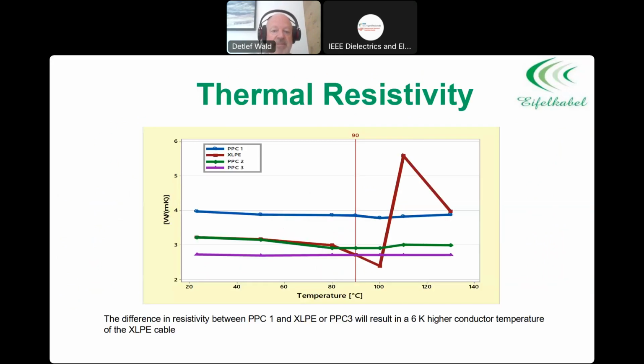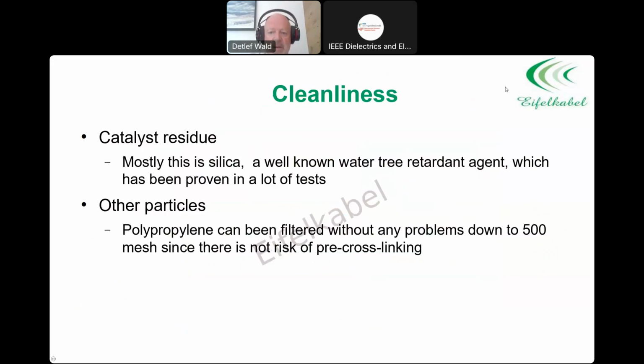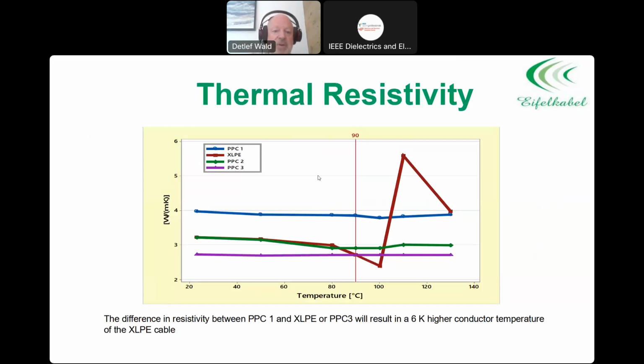Thermal conductivity, the other subject, like I already said, has also something to do with the density. So here's a comparison of XLPE with 3 different polypropylene compounds. The red one with the deep drop, or change, around 90-100 degrees, is the XLPE, and the green and all the other ones are polypropylene compounds. The blue one is a commercial one that is in service. The green and the magenta one are polypropylene compounds under development, where we try to improve the thermal conductivity.